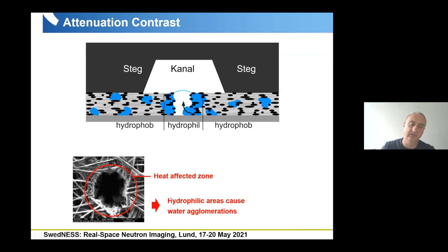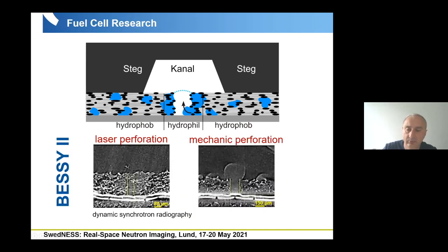And we performed an additional study where it was found out that the drilling process with the laser is leading to some overheating of the material. And this heat affected zone changes its property from hydrophobic to hydrophilic. And finally, we can have the water actually here in the walls of these channels. So at the end, we were able to perform a tomography experiment with high resolution synchrotron radiation,